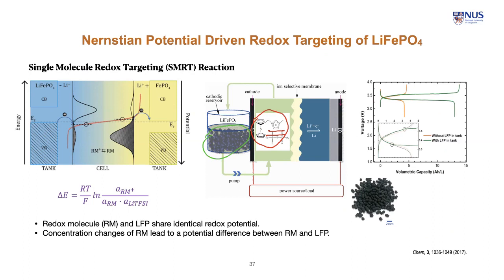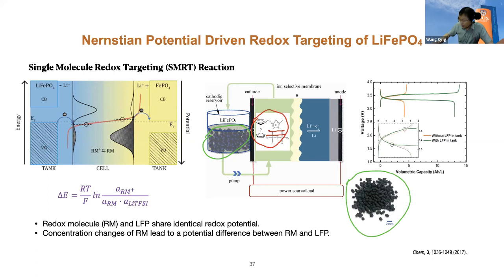But instead of coating the material on the electrode, we make the material into granules and put it into the tank and let the electrolyte containing this ferrocene derivative flow through the system. If you look at the potential of this molecule, it's exactly the same as the material. So based on the Nernst equation, the more the molecule gets oxidized, it generates a potential difference. This potential difference will drive the oxidation of this material. It means the material will be oxidized to become iron phosphate, and the lithium will go to the other side. So that's the charging process.